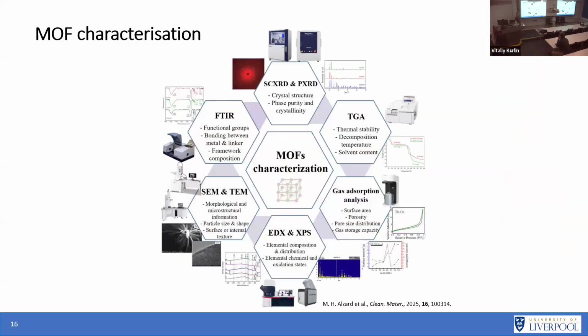In terms of MOF characterization, there are a lot of different areas. I could do a separate lecture on all of these, but I'm not going to, so don't worry. Essentially, when you make a MOF, the first thing you're typically going to do is single crystal diffraction or powder diffraction. This gives you an idea of the crystal structure if you make a crystal big enough. It also tells you whether the thing you've made is pure and how crystalline it is. We'll see a bit later that sometimes PXRD will show you a hump because it's not crystalline. Sometimes you'll get really nice peaks in your pattern, like here.